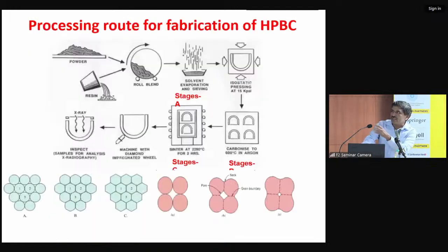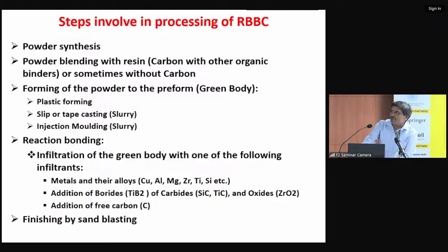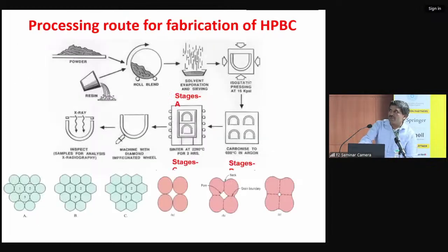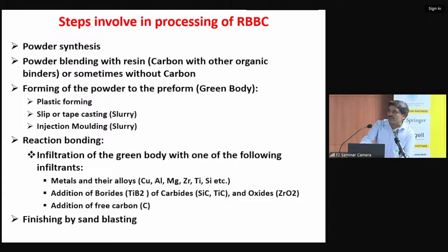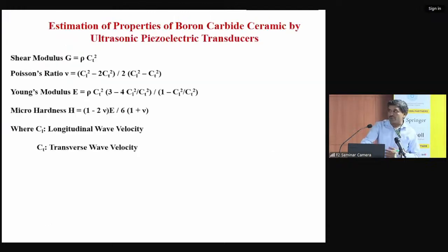So we are starting with the powder, and then we are doing the sintering. There are three grades of the boron carbide. The previous one is the hot press boron carbide, and this is the reaction bonded boron carbide. In the reaction bonded boron carbide, we are first making the slurry. Slurry has the optimum combination of 14 types of ingredients, and that slurry is converted into the green body by injection molding, and then that green body is again sintered in the temperature range of 1600 degrees centigrade to make the product.